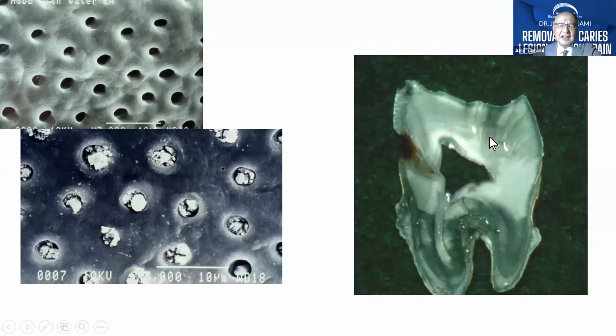By aging, the diameter of the tubules becomes smaller and smaller and sometimes occluded by mineral deposit. Also at the root dentin, because of the lower number of dentinal tubules and the much smaller diameter of the tubules, the so-called transparent dentin is seen very frequently.